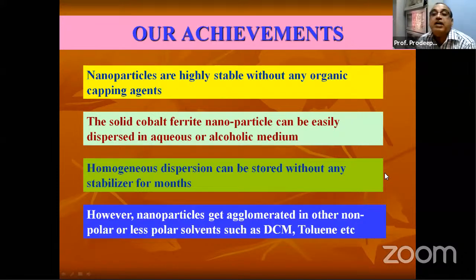Actually, till our synthesis, most of the nanoparticles behaved in the opposite way. They were not dispersible in alcoholic or aqueous medium. In most cases, since they used capping agents, they were mostly dispersible in organic solvents like DCM, toluene, or other organic solvents. But in our case, we have not used any capping agent, and still it is quite stable and dispersible in aqueous or organic medium. So this is the advantage. That means we can do reactions in aqueous and organic medium.